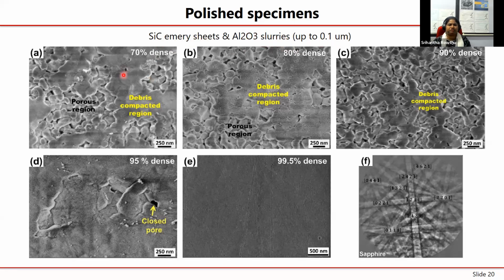Final samples after polishing look like this. For the 70, 80 and 90%, you see that there is a region called the debris compacted region. That is essentially because your polishing is like an abrasive, the mechanism actually is abrasive wear. So it has happened in these regions. This is all tribosintered region, and we can call it the debris compacted region. And still some regions are porous regions.